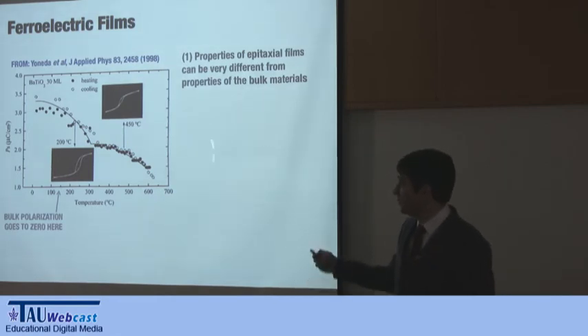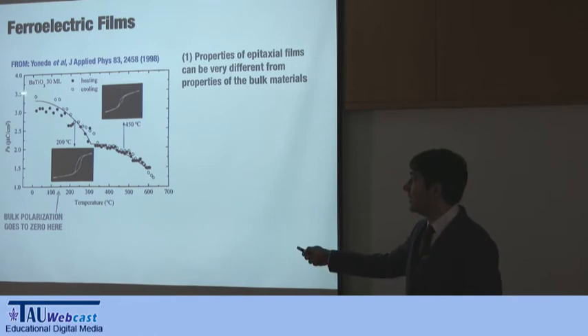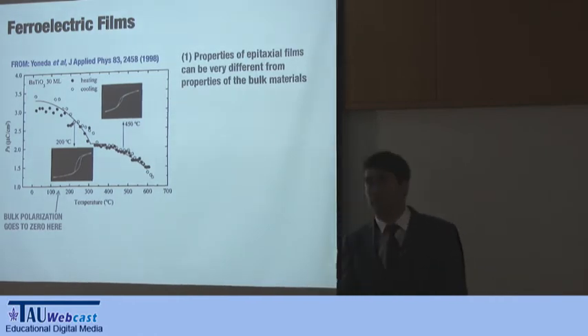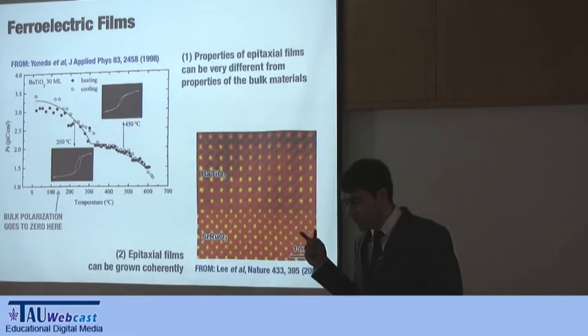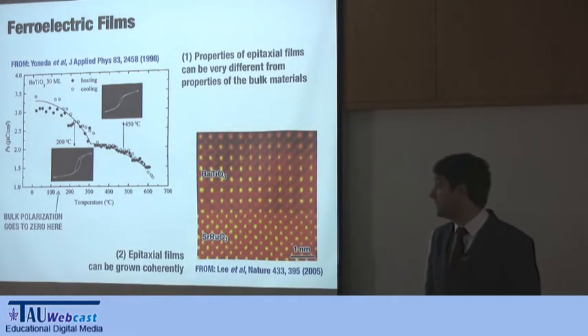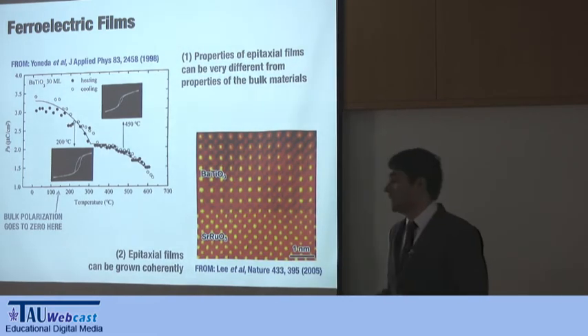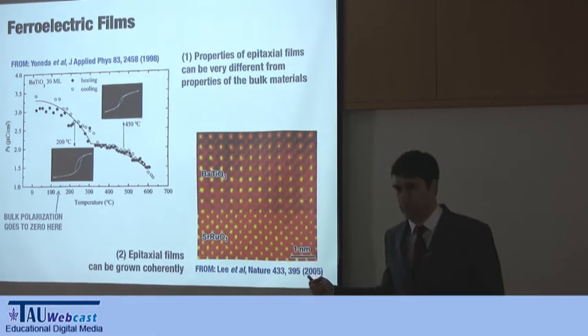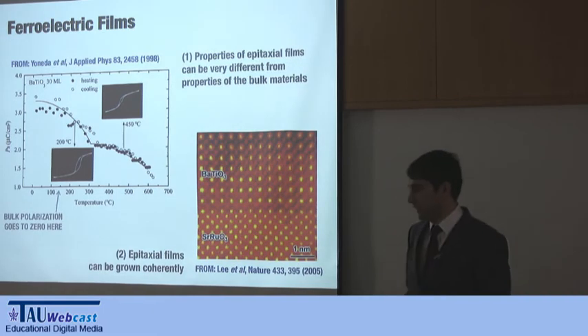And in this case, to show how this changes, for example, if it was bulk, barium titanate goes to zero polarization. The Curie temperature, the one of zero polarization, is around here, 130, 140 Celsius. If you grow it in the right film, you can have polarization, for example, to match larger temperatures. The other point I want to make about ferroelectric films is that they can, in the lab, really be created coherently on top of substrates to a very good degree of perfection.